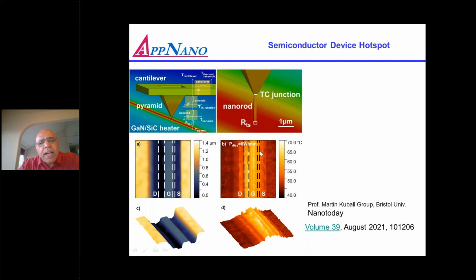They're powering the devices and measuring temperature. You can see the rise in temperature of about 60-70 degrees Celsius when they're powering. So this is again an example that you can go deeper into the nanostructure and still see the hot spots. So this is in the working HEMT devices.